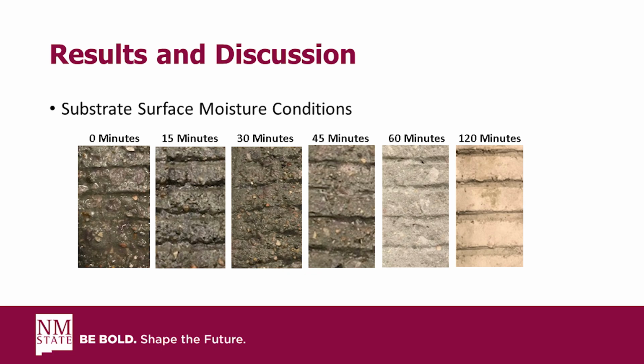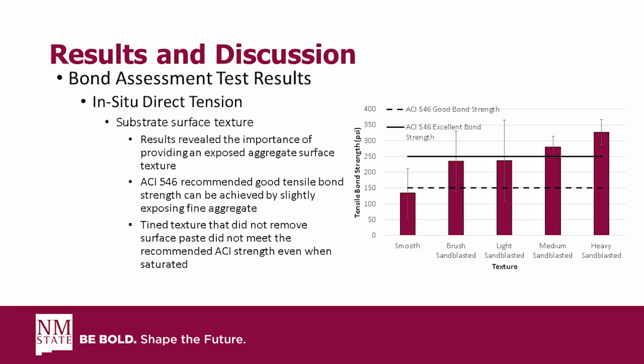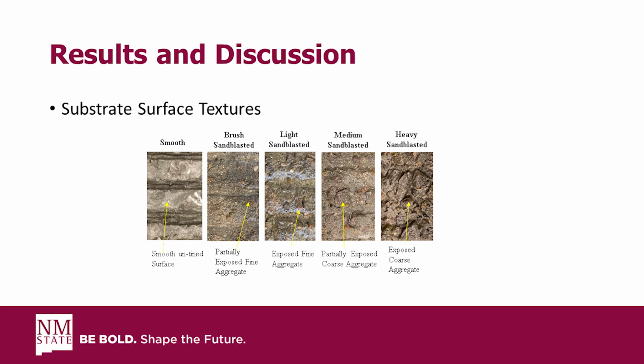Okay. And then here we have the surface texture study. Same thing, we have our ACI 546 good bond strength of 150 psi, denoted with the dotted line, and the ACI 546 excellent bond strength of 250 psi, denoted with a solid black line. Okay, so we can see by providing surface textures, or degrees of exposed aggregate, we get more bond strength. And the medium and heavy sandblasted textures were exceeding that 250 psi.